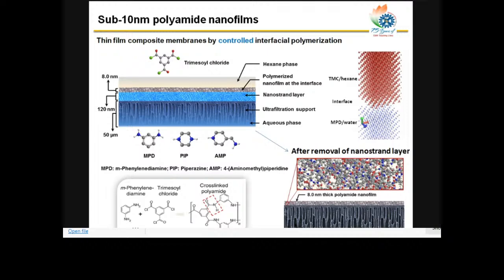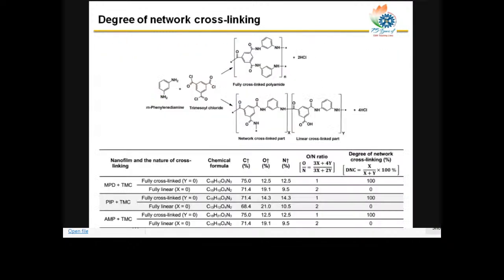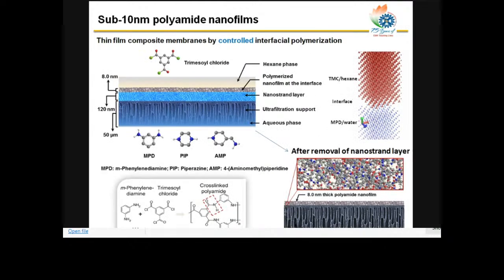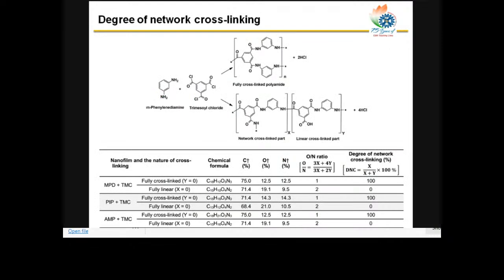So this cartoon, and I think there is a molecular dynamic simulation on the right, on the top corner, but this movie will not work, I guess. So if I go to the next slide here, this degree of network cross-linking is basically, if you took m-phenylenediamine and trimesoyl chloride, depending on the ratio of their concentrations, you can have two different kinds of cross-linking structure. One is fully network cross-linked, that means the top part, and the lower part you have, partially cross-linked and partially linear cross-linked. So depending on the interfacial polymerization kinetics, you can make them highly cross-linked or less cross-linked structure. And depending on that, you will get a different water permeance or solvent permeance through the thin film.